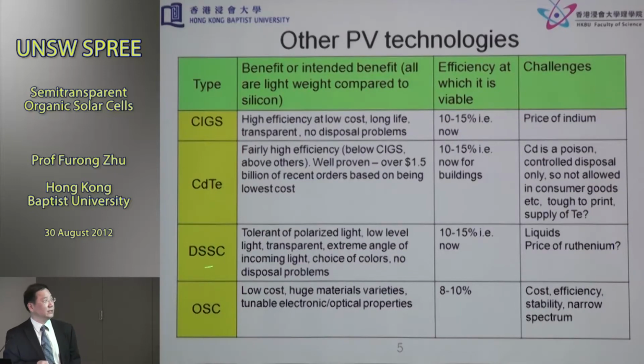This is typically using a solution-based approach, essentially using titanium dioxide materials and dyes, and it works in different illumination conditions. Particularly, it is less sensitive to the angular dependence of the incident light. But in the lab, the efficiency of dye-sensitized solar cells has reached 10 to 15%. But the high efficiency DSSC, or dye-sensitized solar cells, essentially works with liquid electrolyte and ruthenium. This is a very expensive material.